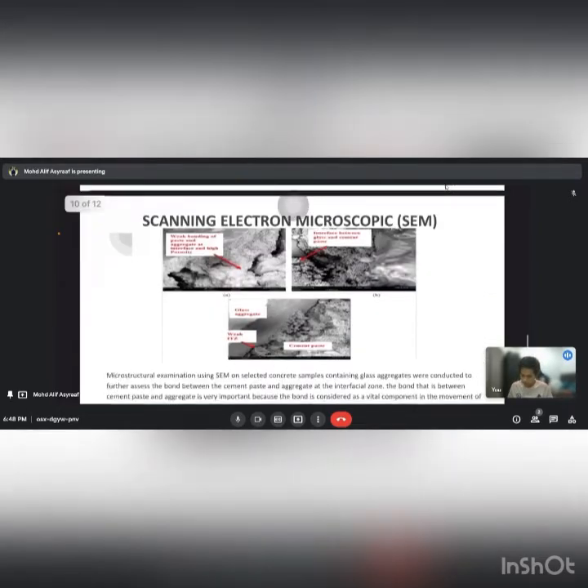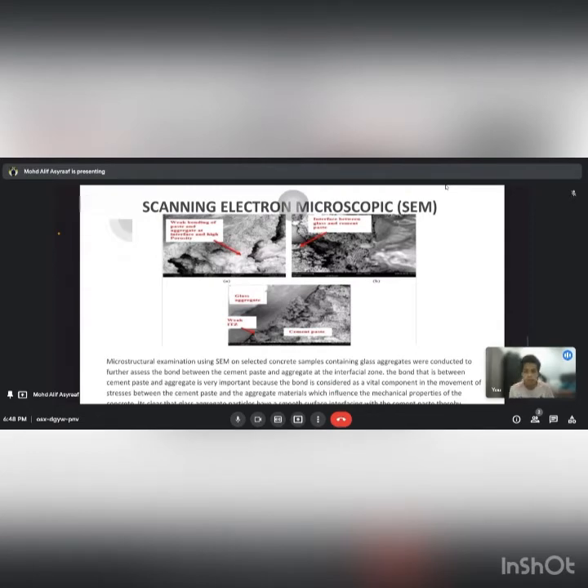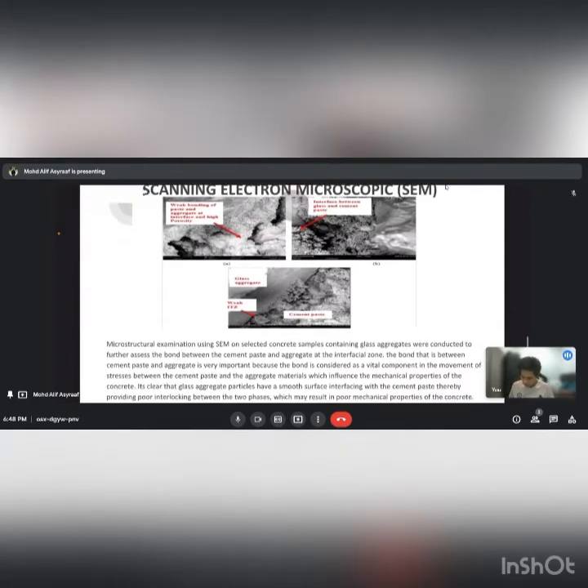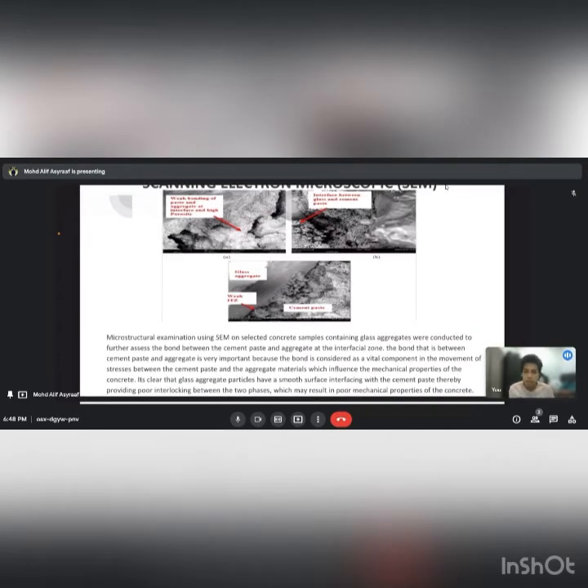transition zone, ITZ. So lastly is from scanning electron microscopy, SEM. So as we can see, the microstructural examination SEM on selected concrete containing glass aggregate were conducted to further assess the bond between the cement paste at the interfacial zone. So the bond with the cement paste is very important, that requires the movement of the stress, so it makes it have many gaps.